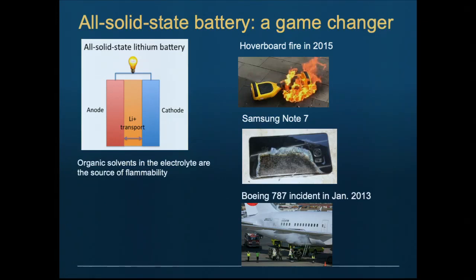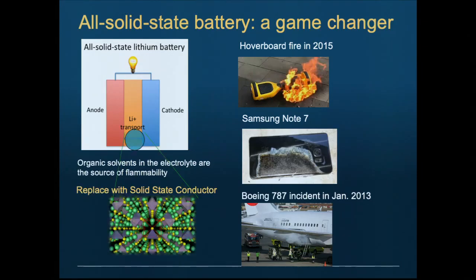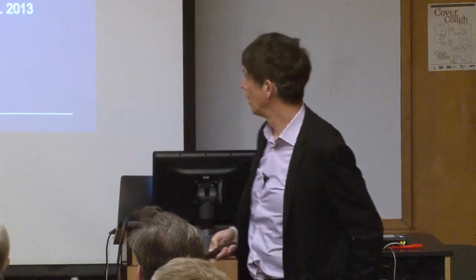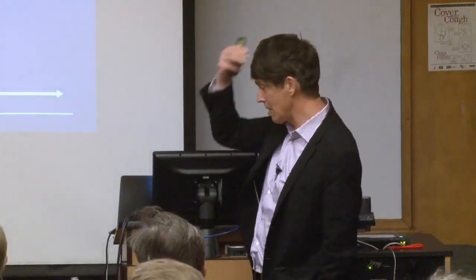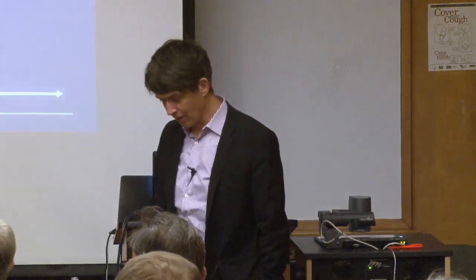The last one was essentially the Note 7 incident. But there have been other ones, like lithium-ion batteries in hoverboards, and like I said, the Boeing 787 incident, which grounded the whole fleet. So the way to solve that is to replace the material with an inorganic solid. If you replace the conductor with an inorganic solid, then in principle it's harder to oxidize, so you don't really have a fuel anymore. And that was thought to be really hard because people always think that you can't make very good conductors, not as good as liquids, but I'll show you that that's possible.